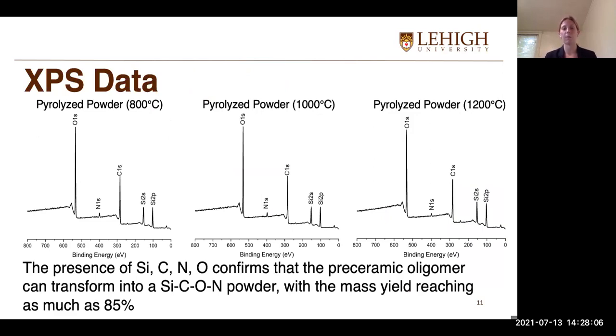So I got this XPS data. Here are the survey scans I obtained, and the presence of Si, C, N, and O confirmed to me that the preceramic oligomer, in fact, can be transformed into a ceramic powder, so SiCNO powder. And this had a mass yield reaching as much as 85%. So this was a really great result for me.